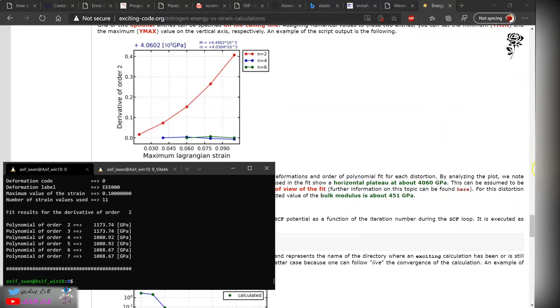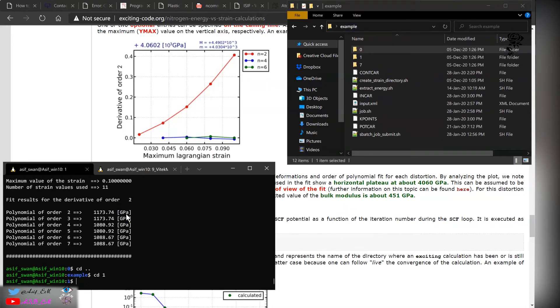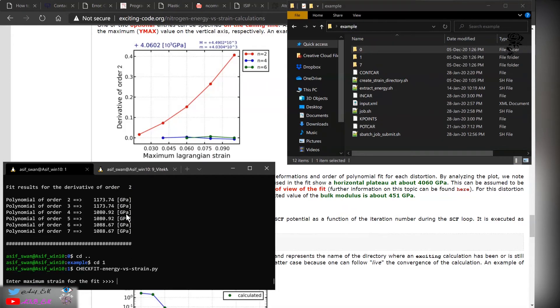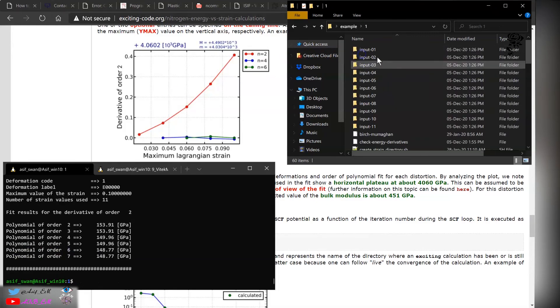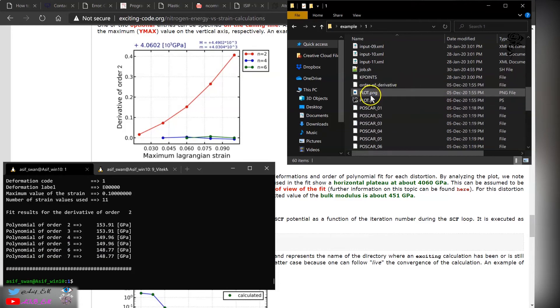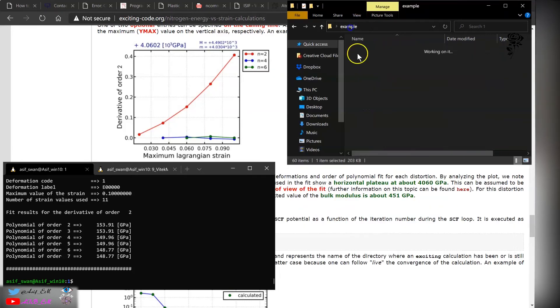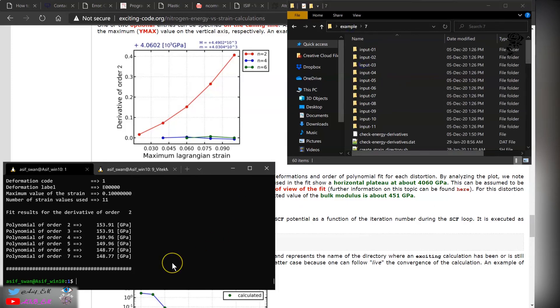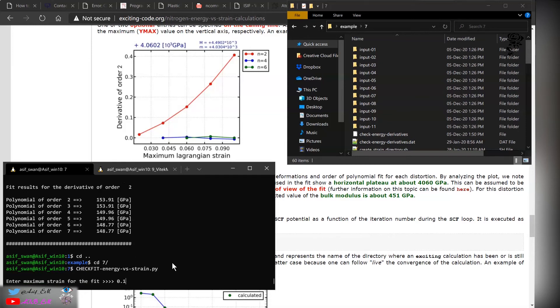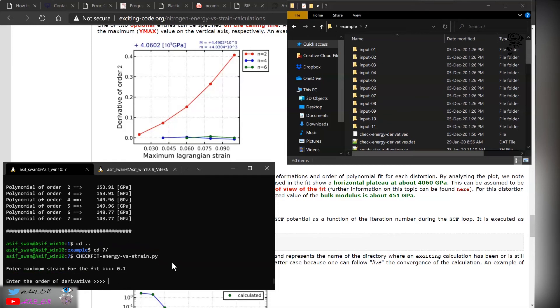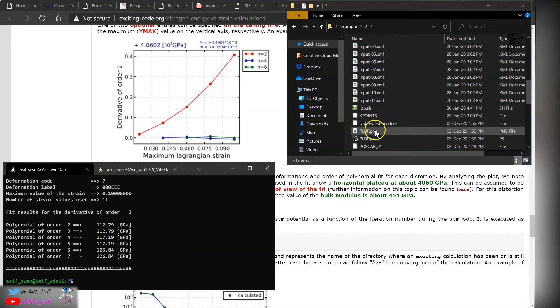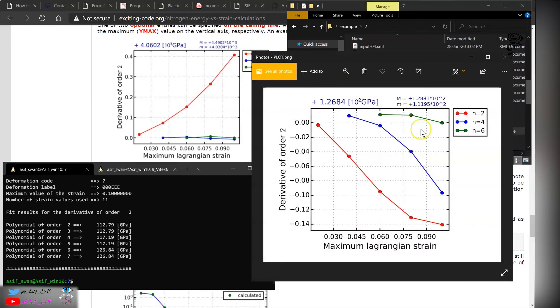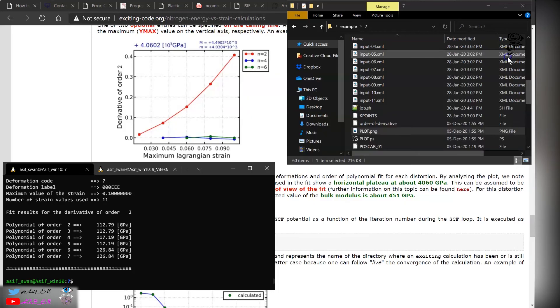We can go ahead and do the same similar analysis for other cases. Again, 0.1 strain value, second order. This one is for the C11 case, and you can see for large there is a large deviation, but the scale is 0.01, almost converged. For the shear case, again I'm using the large value 0.1. For this shear case, the behavior is totally different. Second order, fourth order, and you see it starts to converge. Maybe for smaller values we will see that it might converge rapidly, but you have to do the testing on your system.